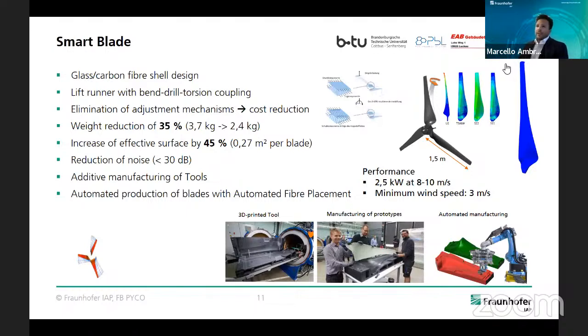We developed a glass carbon fiber shell design. We have a rotor blade system which is 1.5 meters long, so the diameter will be 3 meters. The tower of the wind turbine is around 10 meters high. And you have to know that when we come up to higher winds, at a certain point the machine has to stop. And therefore we usually have some adjustment mechanism in the blades, which are very high in maintenance.